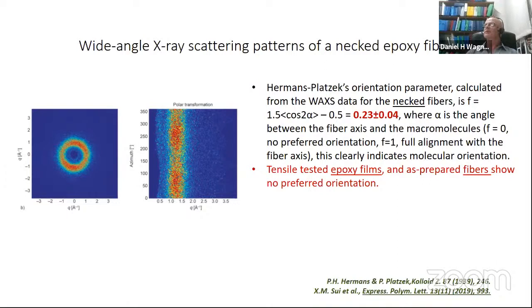but the films usually show no preferred orientation, and the as-prepared fibers do not show the preferred orientation. So really, that means what? That means that the size effect that we observe is different for the as-prepared fiber. It exists because there is a size effect, but it's different than the size effect that we observe with the necked fibers, in which you definitely have some reorientation.